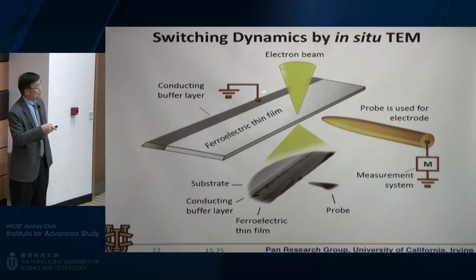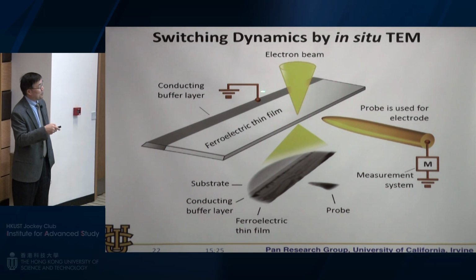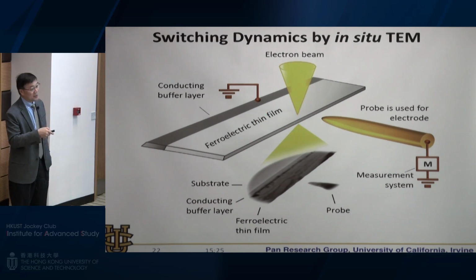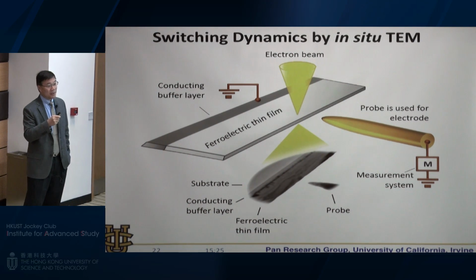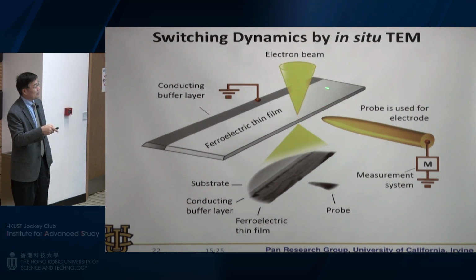We're using a modified Nanofactory holder. We're growing a ferroelectric material as an all-epitaxial, single crystal epitaxial film. The substrate is dysprosium scandate, and the conducting bottom electrode is strontium ruthenate. The ferroelectric is PZT, lead zirconate titanate. All of them have a perovskite structure with a very good lattice match. Therefore, you grow the thin film multilayer structure with a very good lattice match.